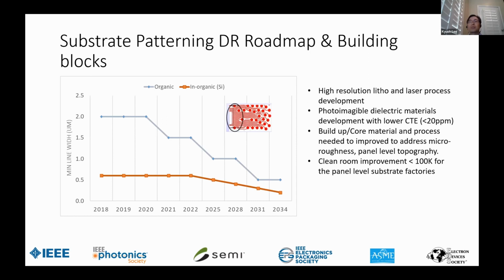And not only the patterning capability, the via scaling is quite critical too. Organic via manufacturing is typically laser via drilling, followed by desmear and electroless seed. That has a certain limitation in scaling the via. So maybe we can go with some photoimageable dielectric that is much more scalable, but it has to have a lower CTE to enable a higher number of build-up layers. And also what we found out was that when you're talking about multi-layer in a larger form factor, a very good clean room environment is quite essential, especially in this litho process. It can be extended to the other wet processes as well.